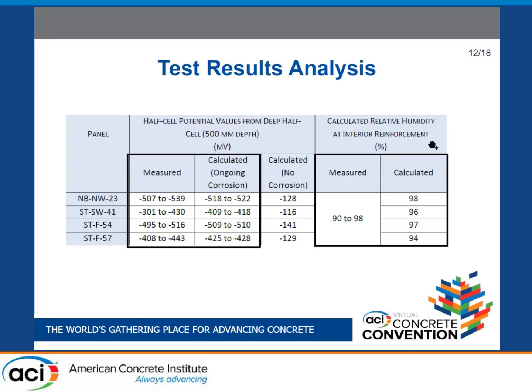Another point: the required relative humidity inside the concrete at the interior steel reinforcement — the steel that we hit first from the inside — should be very near saturation according to our calculations, due to the interior epoxy coating that keeps the concrete near saturation. What we measured was in the low-to-high 90s in terms of relative humidity, which is consistent with those calculations.